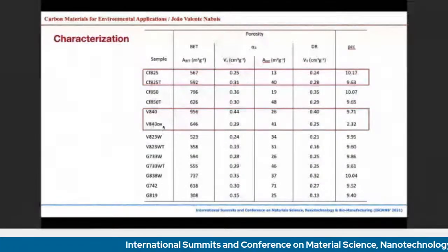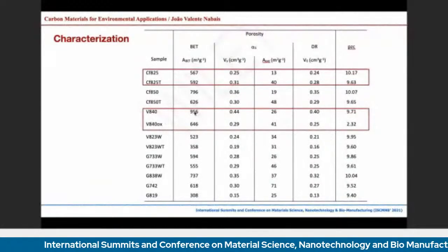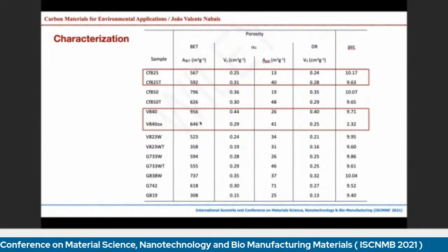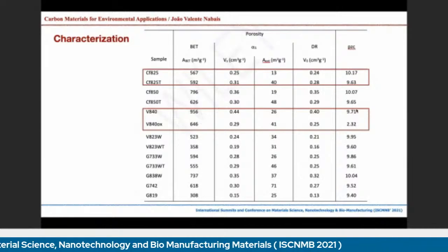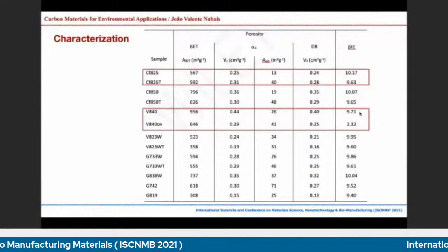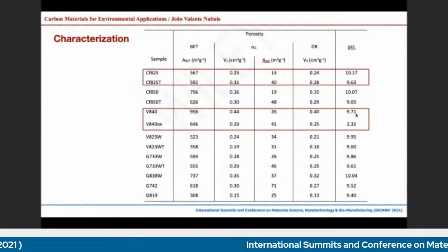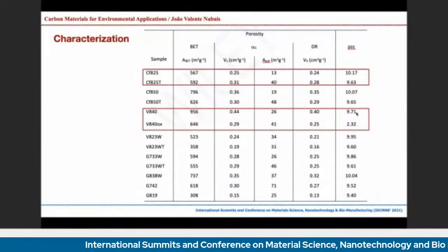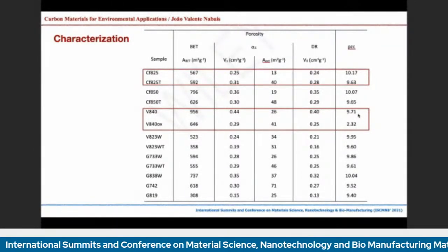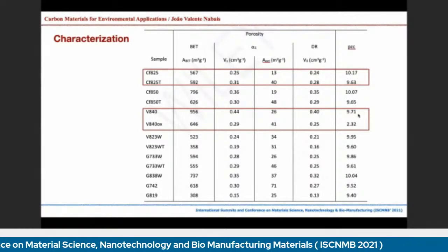Regarding the oxidation, it has a bigger impact on the materials: a decrease in the porosity, but more importantly, a decrease in the pH of the material. So the material went from a basic material to a very acidic material. And this has an impact as well on the characteristics of the carbon, and the surface characteristics of the carbon are highly important for the adsorption of, for instance, inorganic substances.